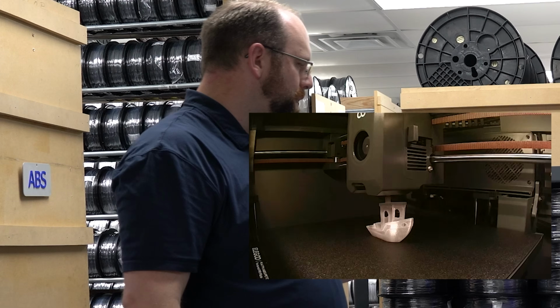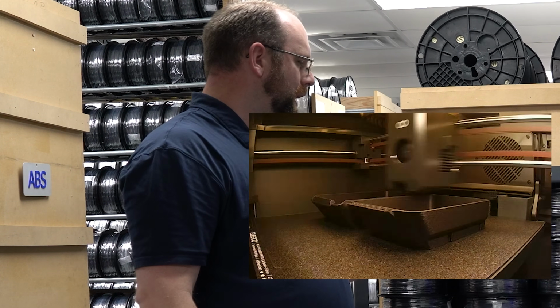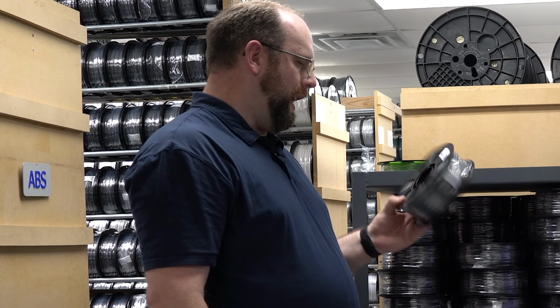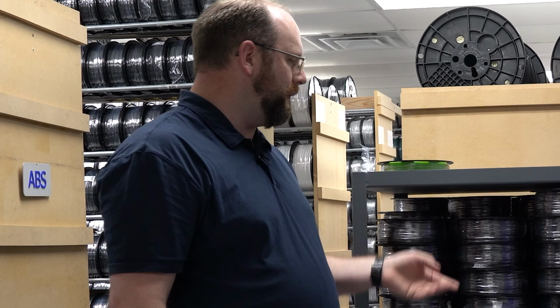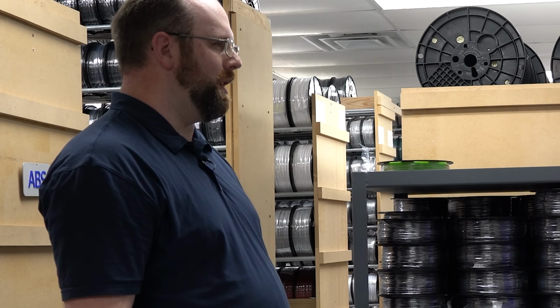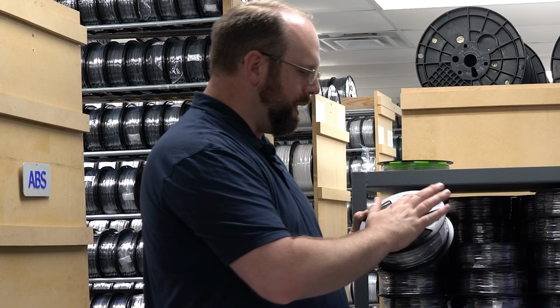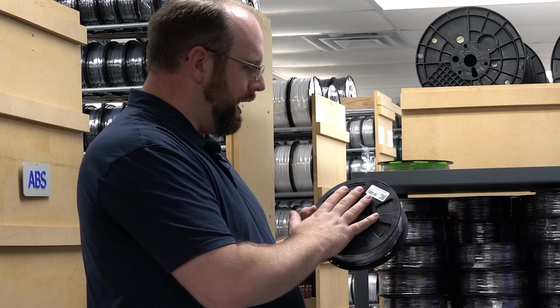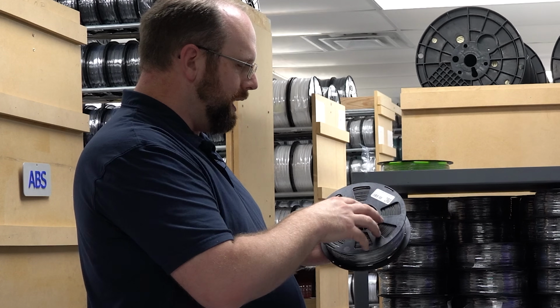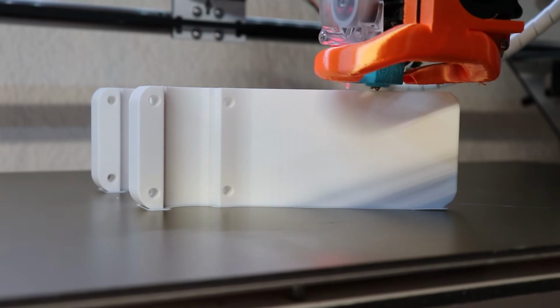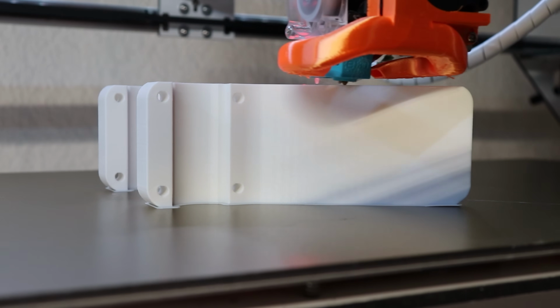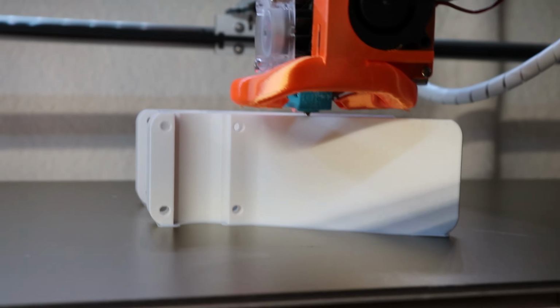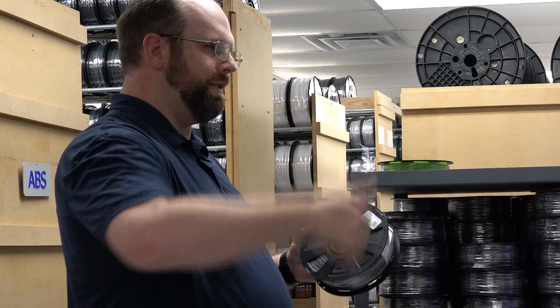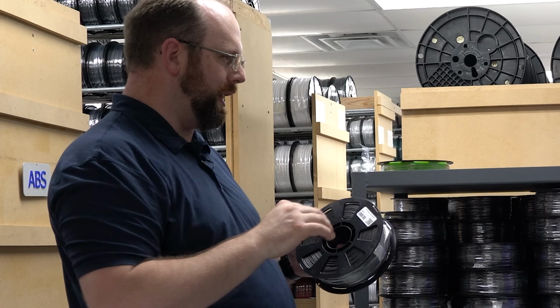Because I print with PETG all the time. I don't have any stringing issues, and I don't dry it. I store it in an open garage, and it's like 50% humidity all the time here in Arkansas, and you just have to get the temperatures right. A lot of moisture hangs out on the surface anyways, and whenever it goes through your hot end, that's the first part that's heated, and most of our 3D printers don't have a tight enough tolerance inside the throat of the heater to trap that moisture in and create pressure that would actually cause a problem. Usually it's just going to vent back out the top of the extruder through the tube and everything. Sure.